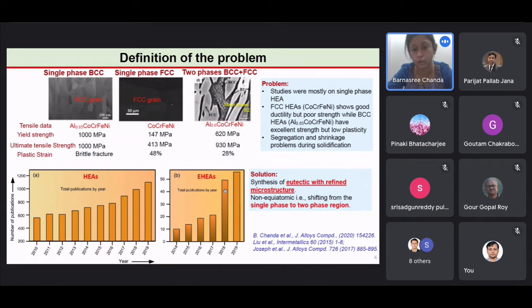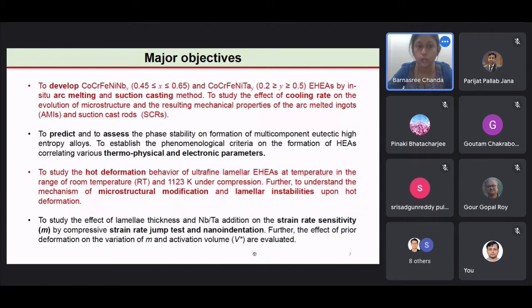We expect alternate soft and hard phases, and to tackle the problem of segregation and shrinkage during solidification. The bar diagram shows, in A and B, the high entropy alloy and eutectic high entropy alloy publications by year, where we see an increase in the research work on high entropy alloys. But compared to overall high entropy alloys, very limited work has been done on eutectic high entropy alloys. So based on that, we have formulated our objectives.